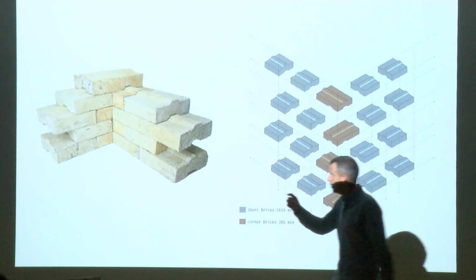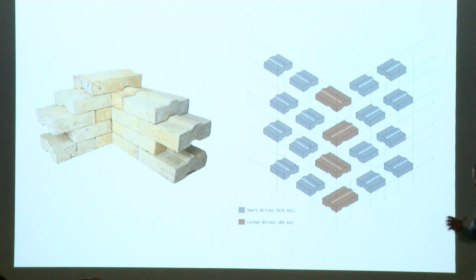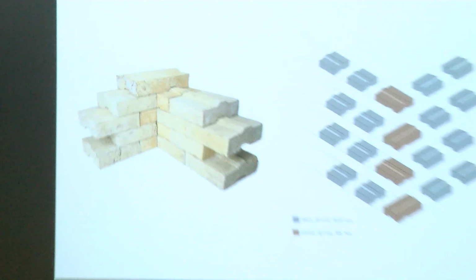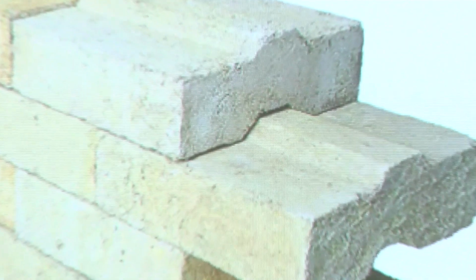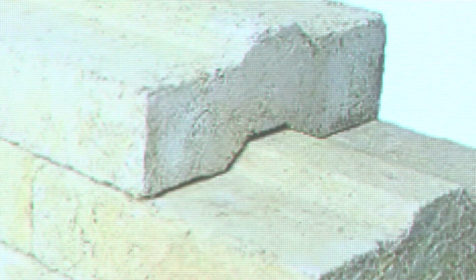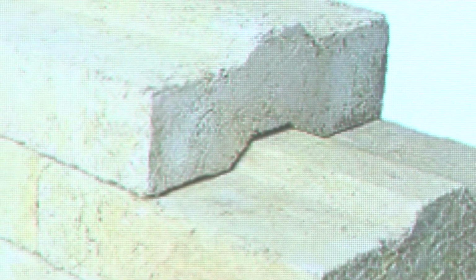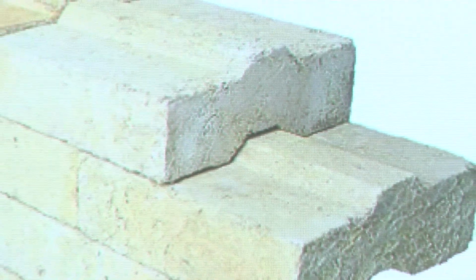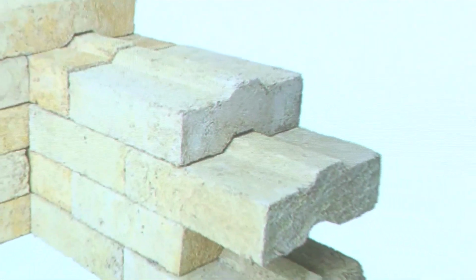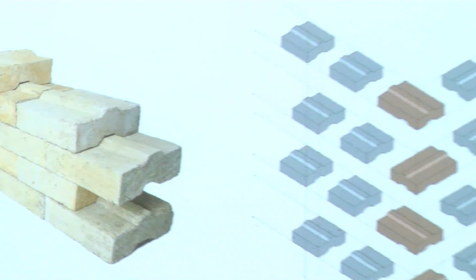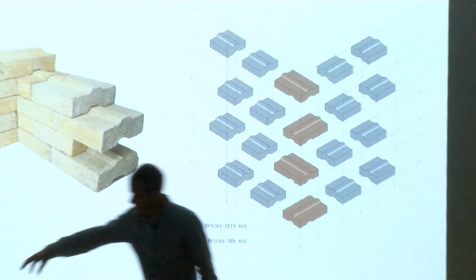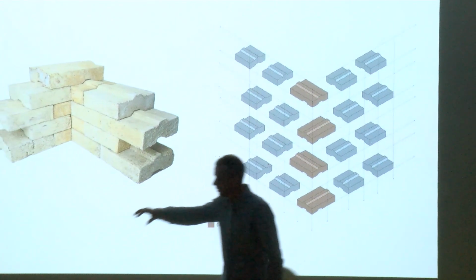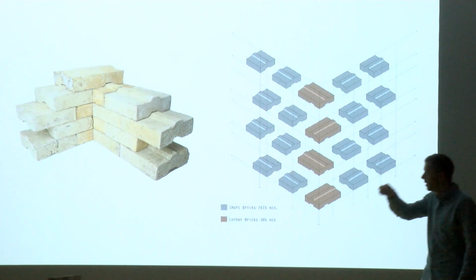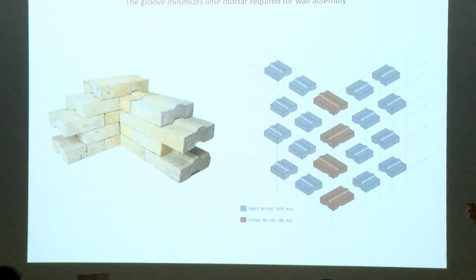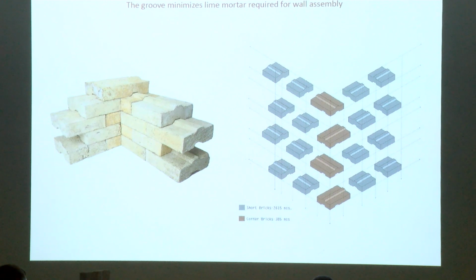And that groove, it seems that it's doing little, but it is assisting the wall in terms of seismic movement by reducing the movement of the wall almost 20% in case of seismic activity. It's also minimizing the amount of mortar that you need to put them together, and it's also assisting with the air tightness of the wall, because the air is not going through the gap, but it needs to do more. Especially, we are keeping a bit of an air gap in the center, so we are putting mortar only on the sides, so that area allows for an additional layer within the system.